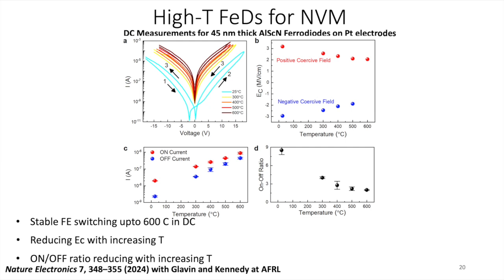And you can again isolate out various parameters from these curves, such as what is the coercive field, what is the on current, off current, and therefore on off ratio. To obtain a stable memory device or do stable computing, you want an on off ratio greater than 1, of course. And a ratio greater than 1 is the minimum required to do any computation. And so we get a stable ratio of more than 1 for up to 600 degrees Celsius. And in some recent unpublished data, we have even increased this number quite well of lately, which we have not published yet. And so this is, of course, DC measurements.